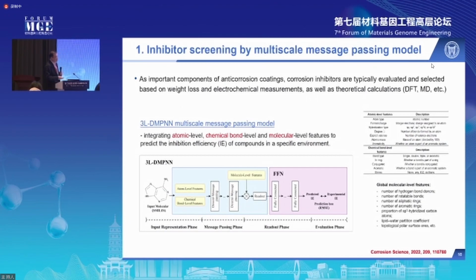And as an important component of anti-corrosion coating, corrosion inhibitors are typically evaluated by weight loss, electrochemical measurements, as well as theoretical calculations. But because corrosion inhibitors are typically small molecules, and there's a large variety of small molecules that can be used as corrosion inhibitors, to identify the correct ones takes a lot of time. And here we develop a machine learning model based on three levels of features: atomic level, chemical bond level, molecular level, and we use these features as the input and inhibition efficiency as the output, for the corrosion prediction.